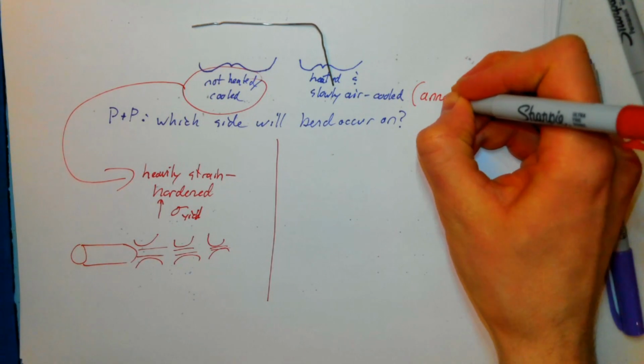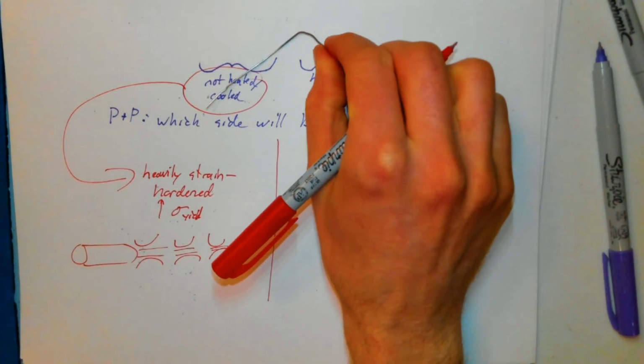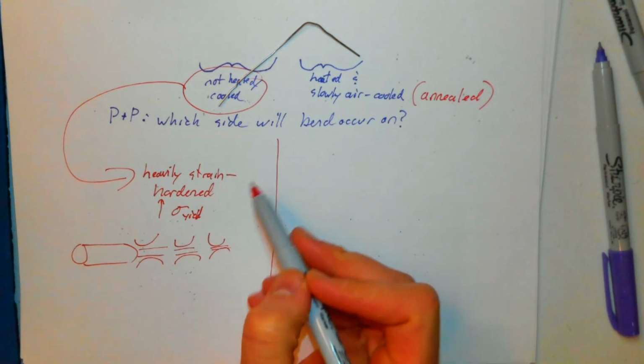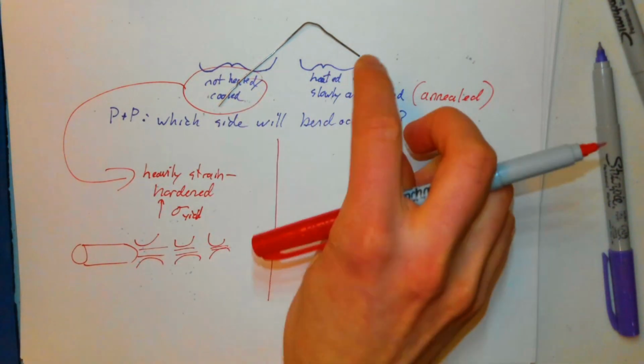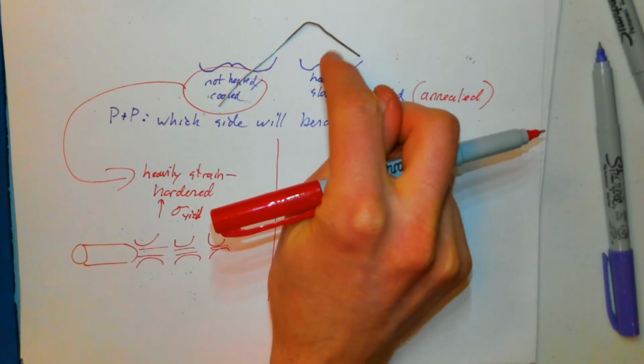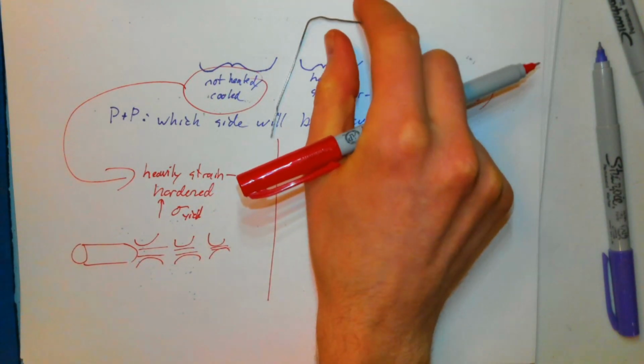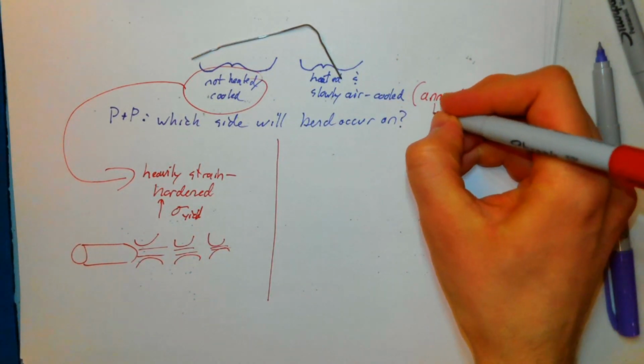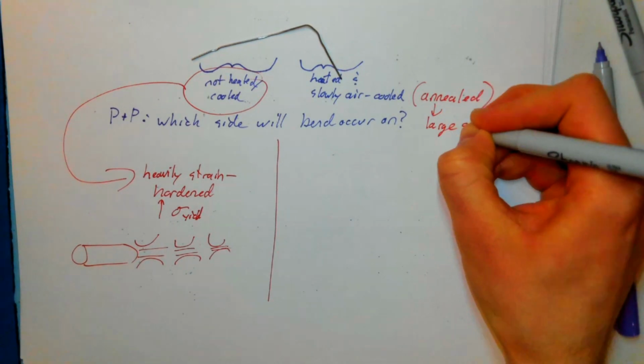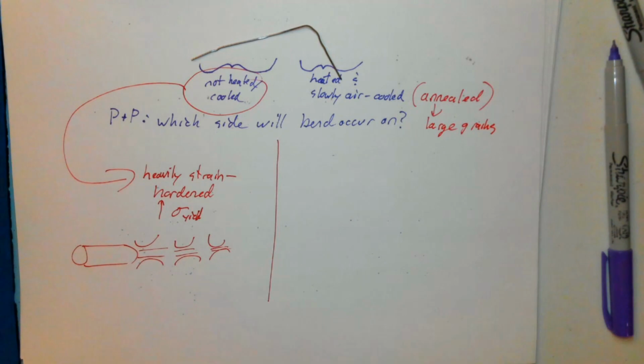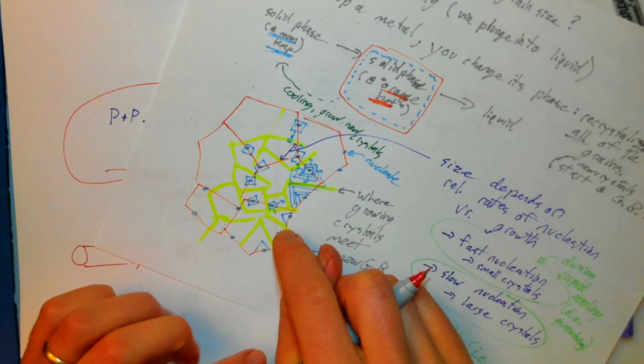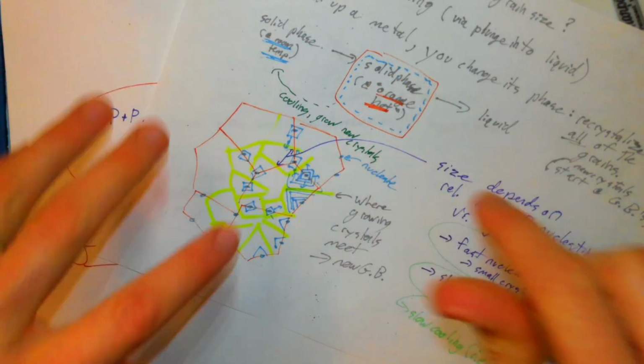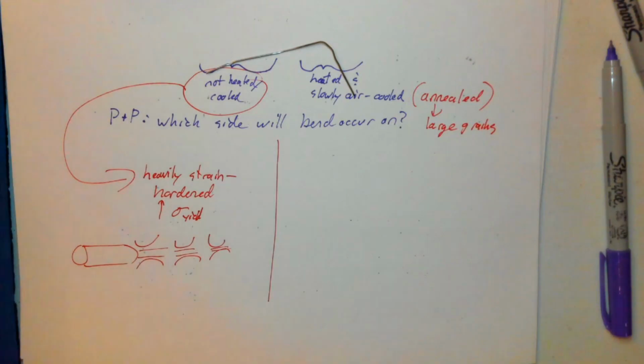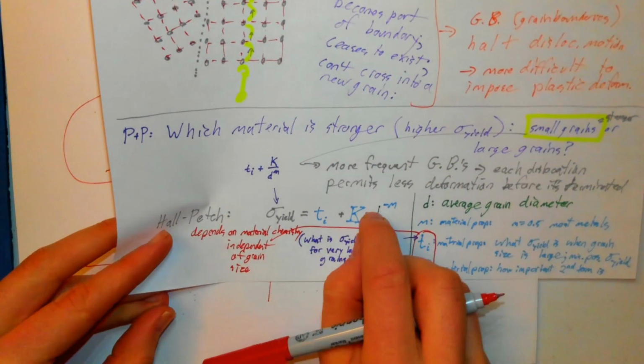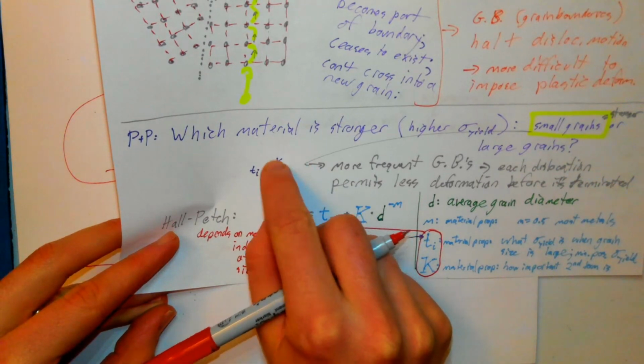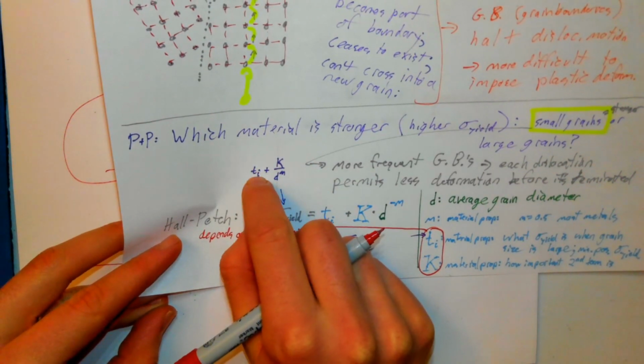I annealed it. So basically I heated it up red hot. I did away with all of the grains. I did away with the small grain structure that was imposed by this process and created a new grain structure with large grains. So I annealed, I got large grains. Rather than having a ton of small crystals all nucleating at once, I only had a few, and those crystals could grow to be really big before they took over. And of course, if we go back to Hall-Petch, if we have a really big diameter crystal, then our yield strength goes back down towards σ sub i.